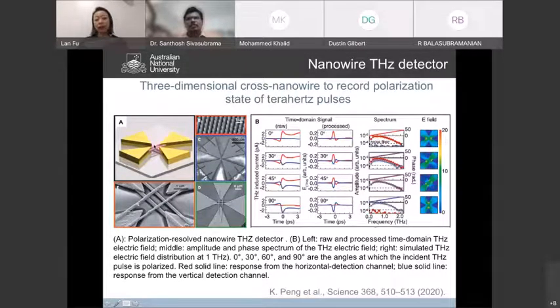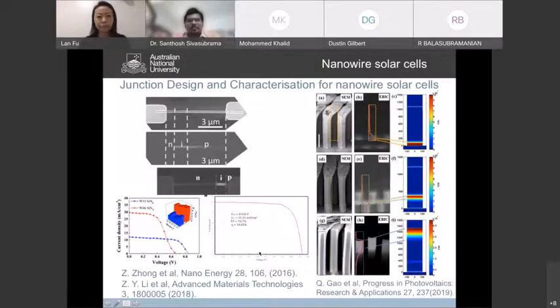we cross-contact two nanowires, because nanowires have this one-dimensional geometry and a very nice polarization response to the terahertz signal. So by fabricating this cross type of terahertz detector, we will be able to record the full polarization state of a terahertz pulse. This is also a very interesting extension of the work that we demonstrated from the single nanowire terahertz detector.